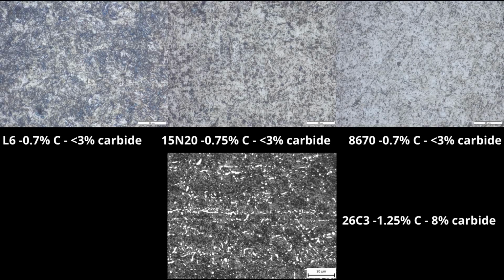Okay, so we talked about hardness and toughness. These nickel steels can be pretty good in that regard. But in terms of wear resistance and slicing edge retention is where they sort of fall down. Now, because these steels have about 70 points of carbon, they have little or no carbide remaining in the microstructure after heat treatment. Carbides are hard particles formed between carbon and a metal, and those hard particles are what give your steel wear resistance beyond just the hardness of the matrix.